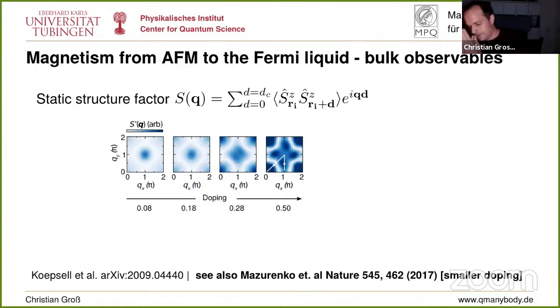So first, when we now move away from half filling, the question is, what does the magnetic order do? Magnetic order you can either measure, as I showed you before, with standard 2-point correlations, or you can sum up all the 2-point correlations with the wave vector that corresponds to it. You do a Fourier transform and sum all the components up, and that gives you the static structure factor. And that static structure factor we measure in doping dependence. This is what's shown here. So you have the Qy, the Qx here that you get from the Fourier transformation, and you see the experimental signal here in arbitrary units, because there's a normalization to show the signal. We also kill the Q equals 0 to make this more visible. So it's about the structure in momentum space, and not about the amplitude, what we are doing here.